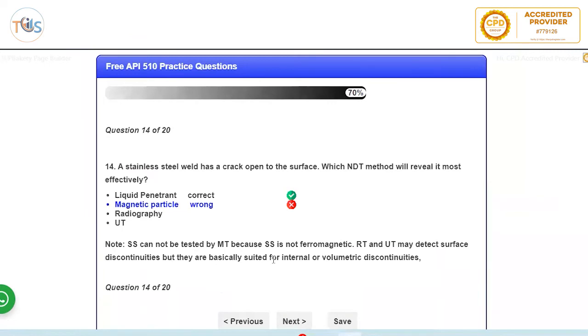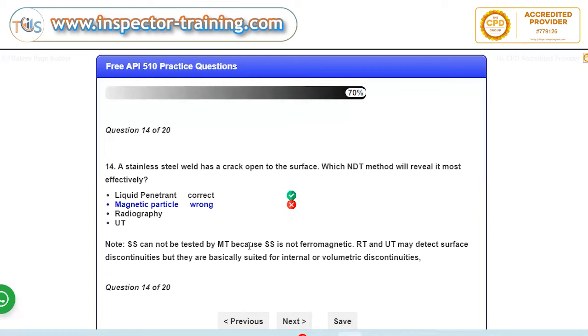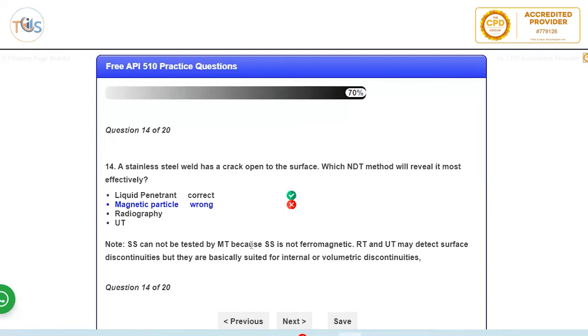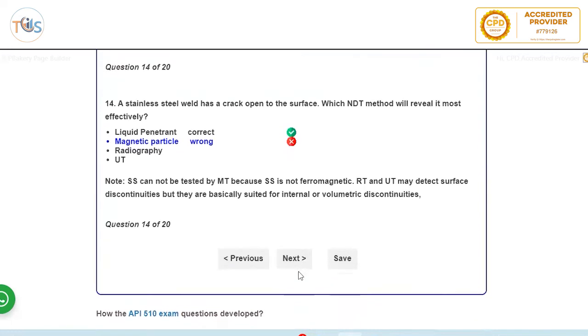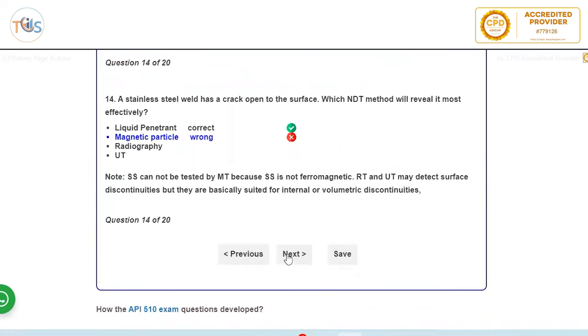Stainless steel weld has a crack on this open to the surface. So if it's open to the surface, the most sensitive one is actually liquid penetrant. And now UT, probably you might not get it because UT is not very good on detecting defects close to the surface or on the surface, open to the surface. Whereas radiography, I mean it's more expensive and anyway liquid penetrant is more accurate in this case. Compared to magnetic particle, the magnetic particle does surface defects or open very close to the surface, but liquid penetrant only does defects that are open to the surface. That's it. But then it's also very sensitive and very more effective to do that.